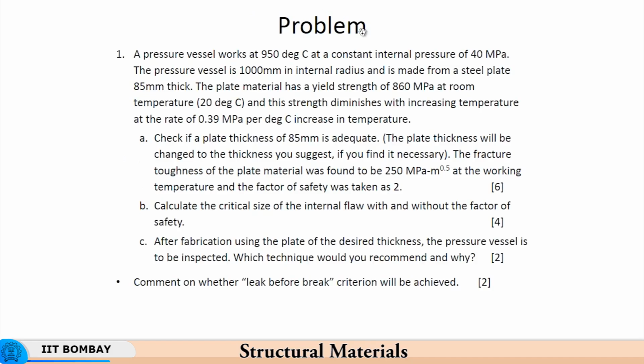So, let us take a problem now pertaining to a pressure vessel which works at 950 degrees centigrade at a constant internal pressure of 40 MPa. In this kind of case study, it is basically a problem of designing the thickness of the pressure vessel using two different criteria, and we will see how insufficient the criteria pertaining to yield limited design and fracture based design would be when it comes to preventing failure by creep. So, let us go through this problem and then come to the issue of creep.